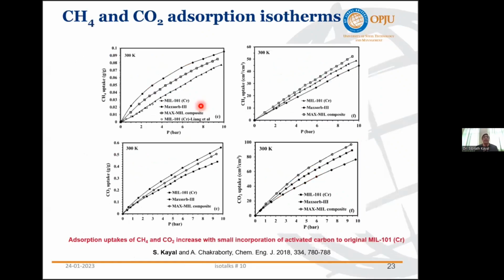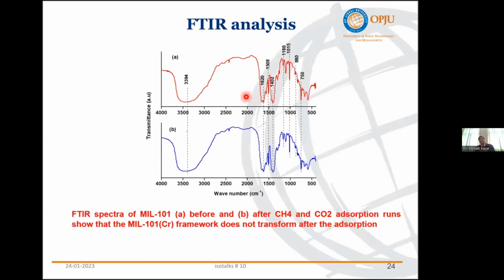And this is the comparative study at room temperature, where for the composite materials, the adsorption capacity actually increases under the same conditions. Now, this FTIR analysis we performed to investigate whether there is structural deformation of the MOF structure after the adsorption of methane. For that, we did the FTIR analysis, Fourier transform infrared spectroscopy, before methane and CO2 adsorption and after methane and CO2 adsorption.